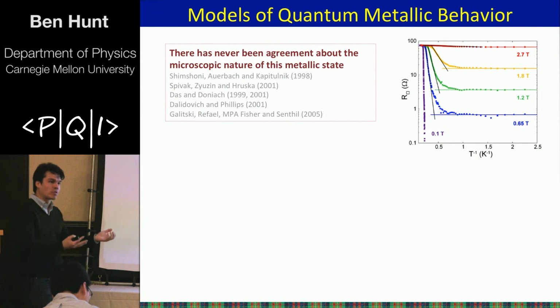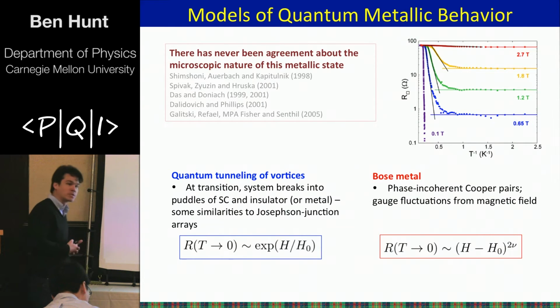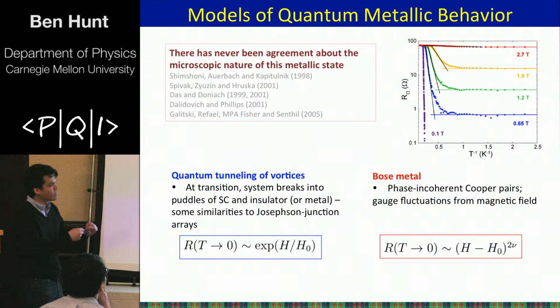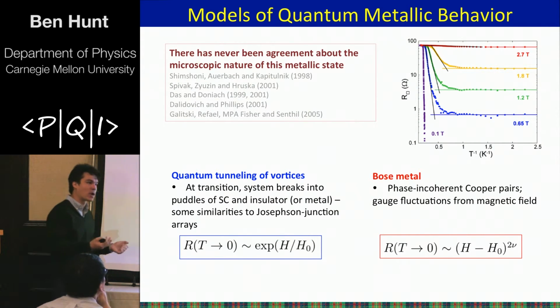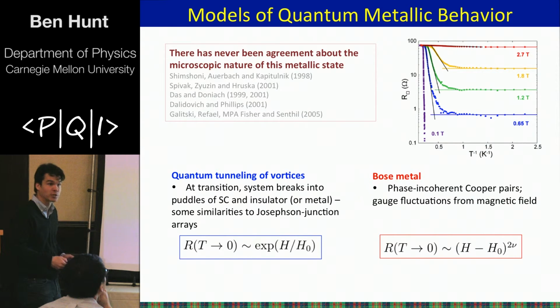One is that it's some sort of tunneling of vortices at low temperatures. The system may break up into puddles of superconductor and normal, and the vortices may tunnel between those various puddles. And if the vortices are tunneling and coupling to a fermionic bath, then maybe you could get some dissipation and some finite resistance.